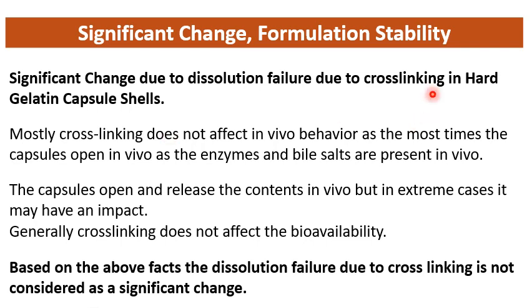Significant change due to dissolution failure due to cross-linking in hard gelatin capsule shells or soft gelatin capsule shells will not be considered as a significant change, because mostly cross-linking does not affect the in vivo behavior, as most of the time the capsule will open in vivo as the enzymes and bile salts are present in the GIT. The capsule opens and releases the contents in vivo, but in extreme cases it may have an impact. But that is only in extreme cases, which can be treated on a case by case basis.